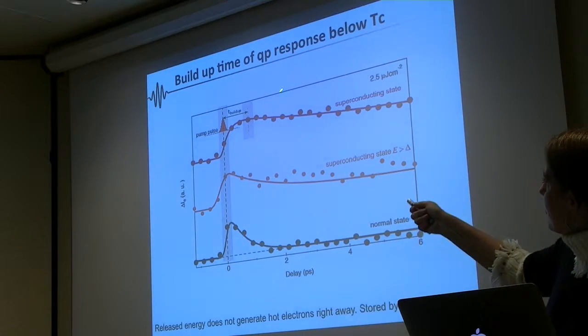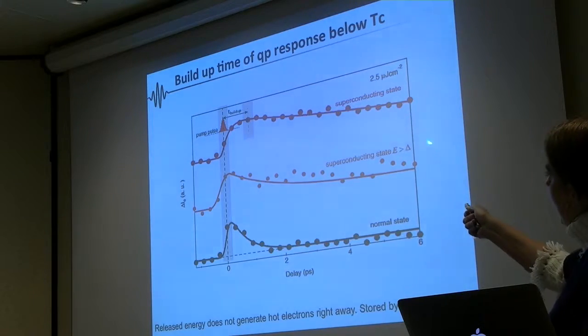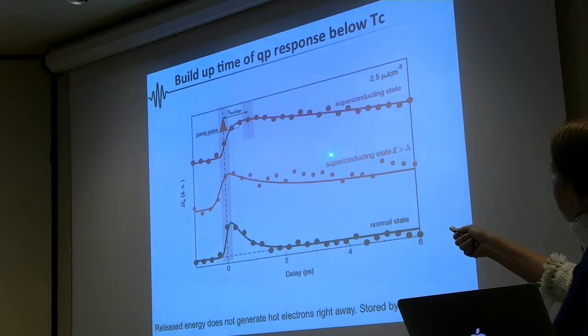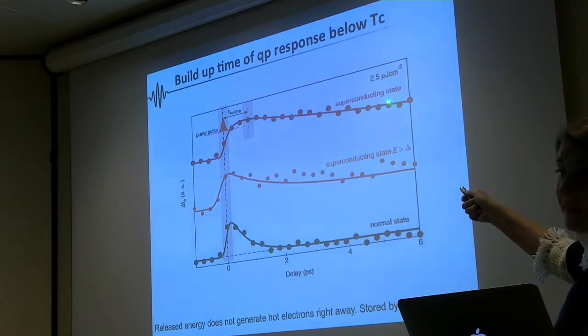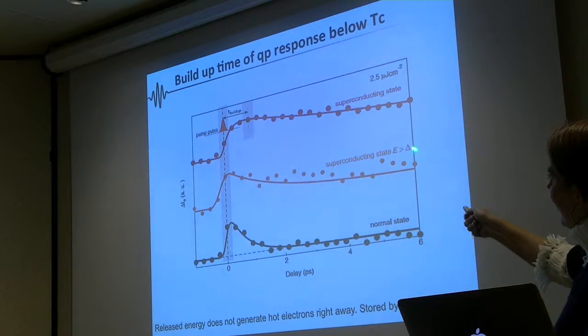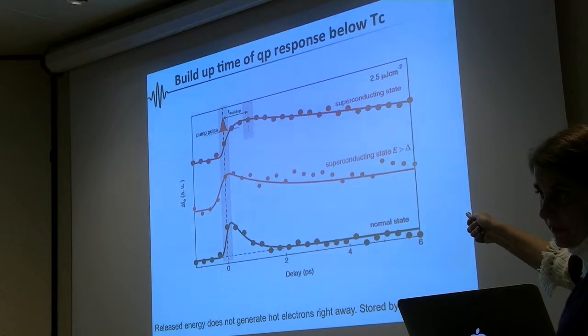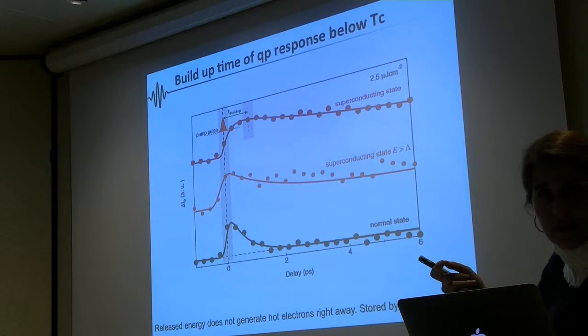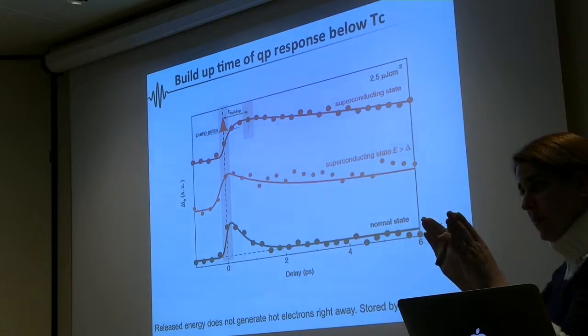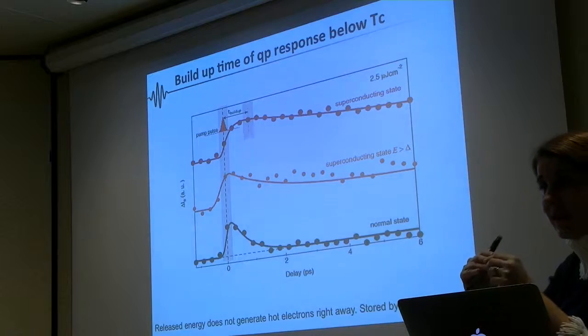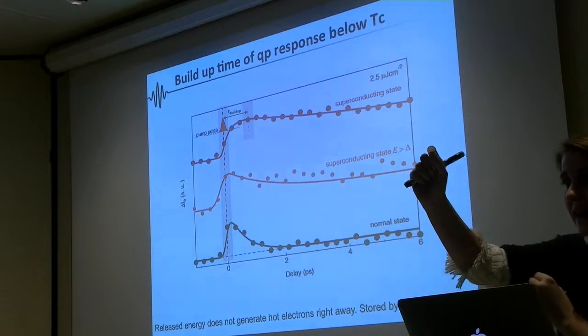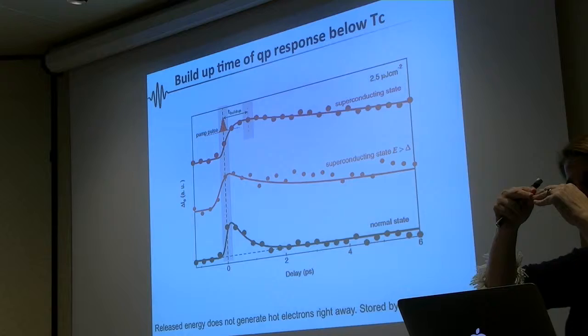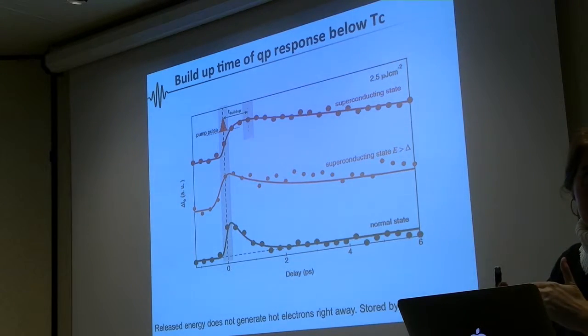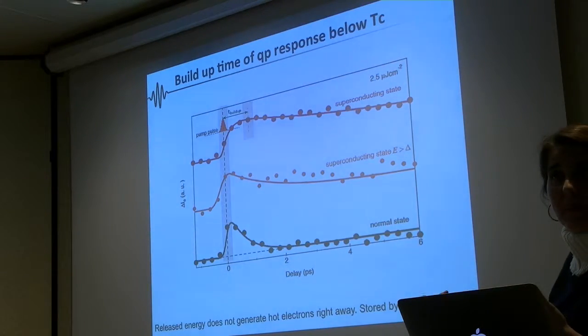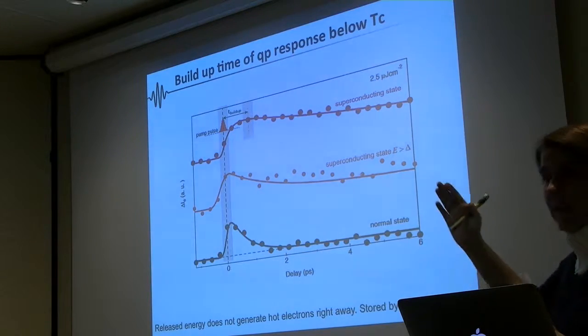And then what is very interesting, you see, same experiment, same everything, but if you are measuring now, so this is in the superconducting state. This curve is here also in the superconducting state, but it's for energy bigger than the gap. So one advantage that photoemission has, I have selectivity in momentum, and I have selectivity in energy. So I can sit at the Fermi level, I can sit inside the gap, I can sit at a state well down in energy where the gap is closed. And I can study the dynamics.